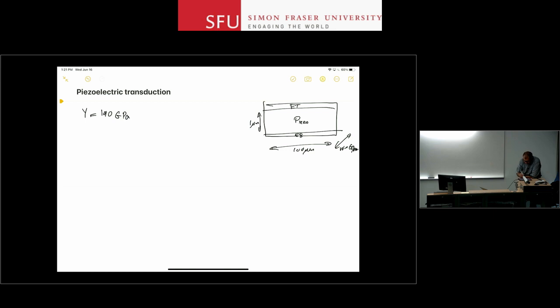We are interested in the bulk extensional mode of the vibration. In this vibration mode, the device becomes longer and shorter, right? So linearly, across that longer dimension, it becomes longer and shorter. My field is between these two. So I'm interested in D31 in this case. D33 value is given, but D31 is the one that is going to basically operate the device at the mode that I want. It's 2 picometers per volt. The relative dielectric constant is given to be 100.